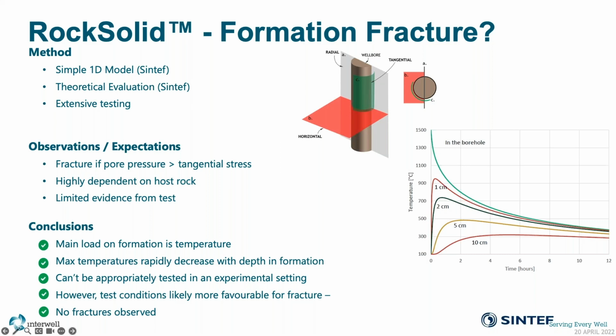Test samples indicate that the heat effects of our reaction only reach plus or minus 1 inch into the borehole interface. We have core samples cut open that we have investigated this with to provide evidence that you can see the heat effect within that 1 inch of that borehole interface.